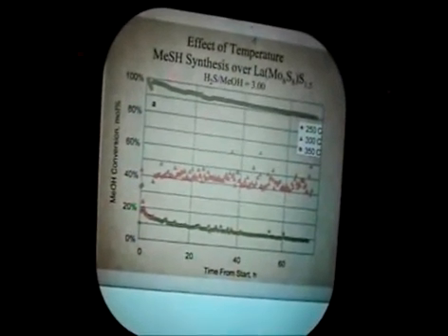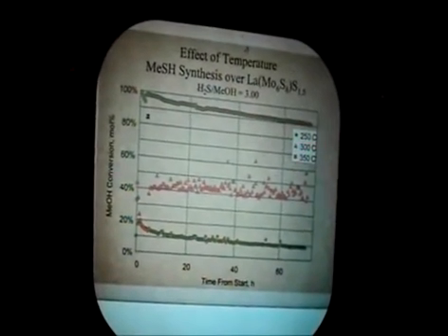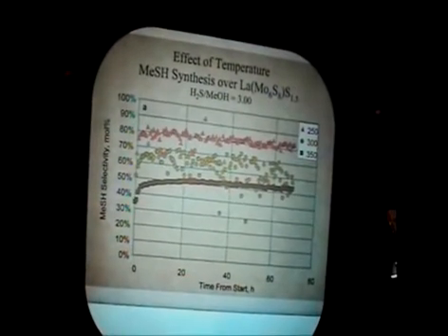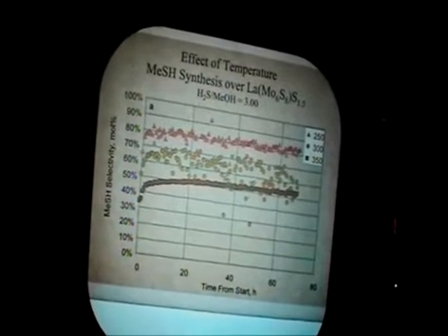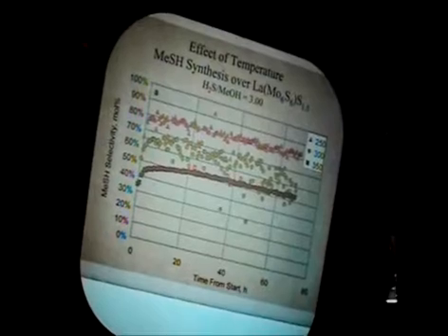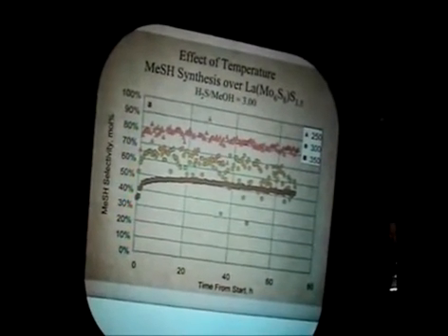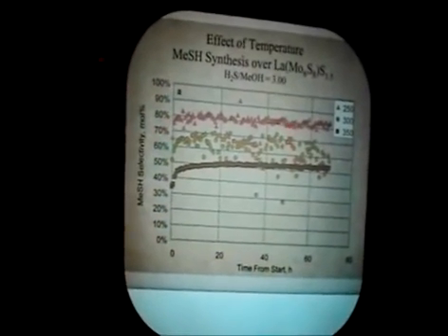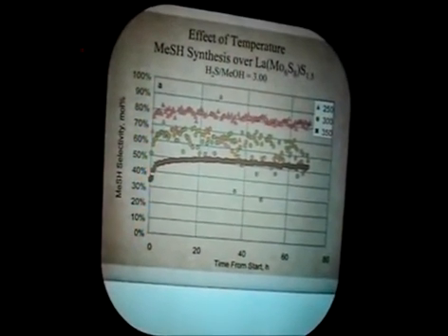And the stability, you can see there's still some slight deactivation after 3 days online. And the selectivity to methanethiol under these conditions is interesting. It actually increases at the beginning of the reaction and then tends to stabilize. And notice also that as we increase the conversion by raising the temperature, the selectivity to methanethiol decreases. I have a summary of those results in a table in a second.